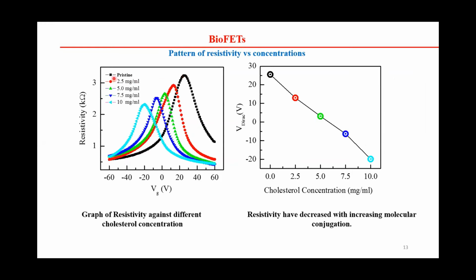And when we immobilize this transistor, or this channel, with some kind of analyte, this is the concentration of the analyte. We can see that the shift in the transition peak, or in the charge neutrality point, can be clearly observed. And when we increase this concentration, we can see that the change is more prominent. So by doing that, we can also detect the concentration of the analyte.